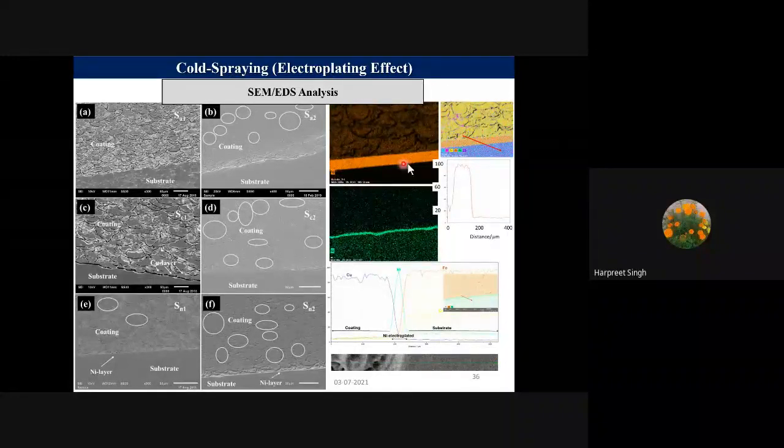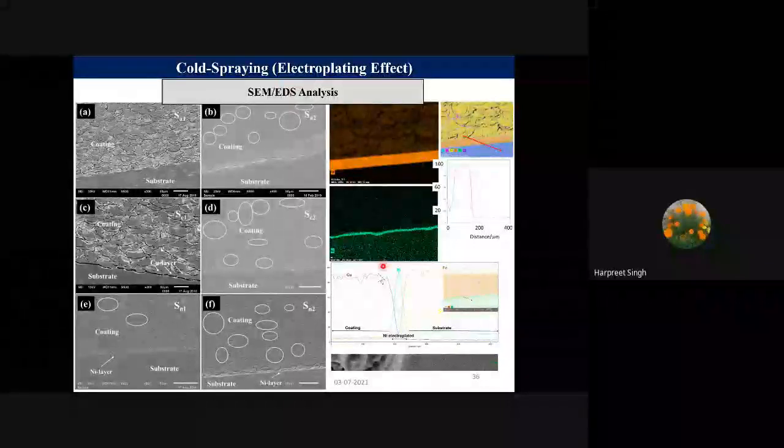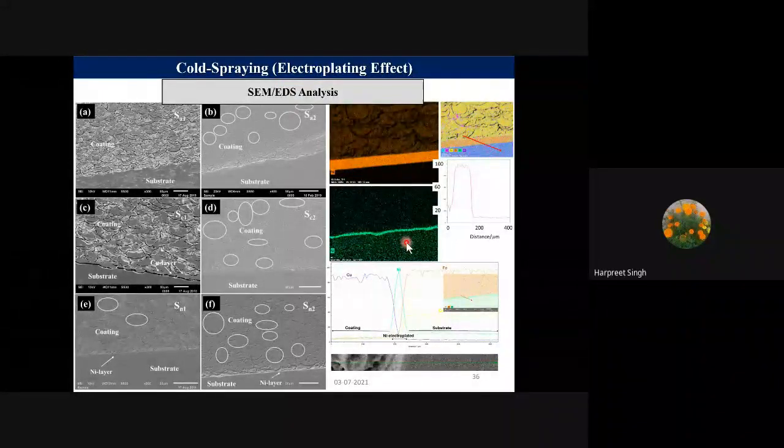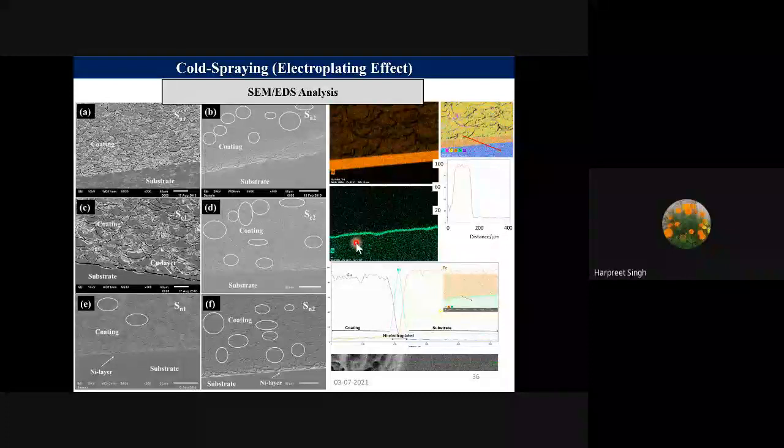And similarly here nickel, in one other case nickel. This is another case. See, this case basically refers to this one itself, because one of the practical challenges was that we wanted to deposit the interlayer of copper, but copper cannot be deposited on the substrate through electroplating directly.